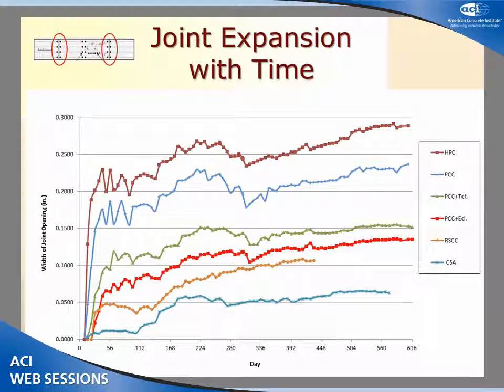Here is the graph for all the slabs and mixes we used, showing the joint expansion. At the top we have high performance concrete, which shows the largest expansion, and at the bottom line we have shrinkage compensated concrete, which shows a very low shrinkage or joint expansion for our slabs on ground.